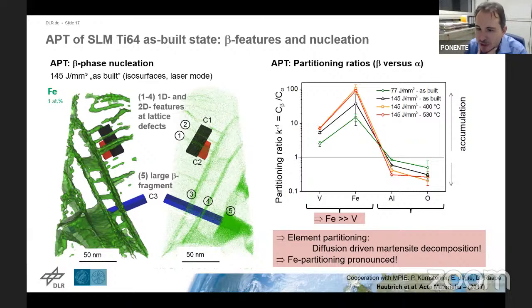So in summary, we find that the heat treatments lead to a diffusion-driven martensite decomposition and the stabilization of the microstructure, so that at higher heat treatment temperatures, we end up with stabilized alpha-beta microstructures.